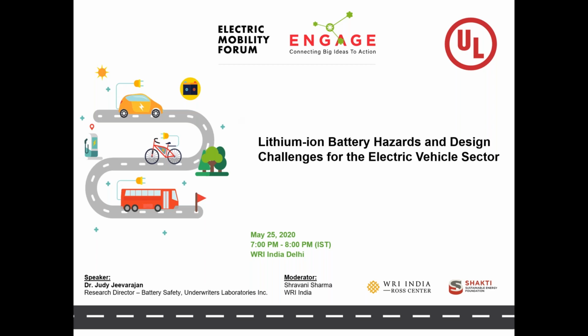So keeping the battery at a stable temperature closer to ambient, which is about 20 to 25 degrees C, will not only save the battery in terms of its health, but it also gives better performance and longer life. To do that in extreme environments like very hot or very cold temperatures, you need external features like cooling systems and heating systems to keep your battery under that same conditioned thermal environment. So I would say, for extreme hot weather, one needs to have an active cooling system that will provide cooling continuously to the battery. And in terms of very cold temperatures, you have to have a heating system.